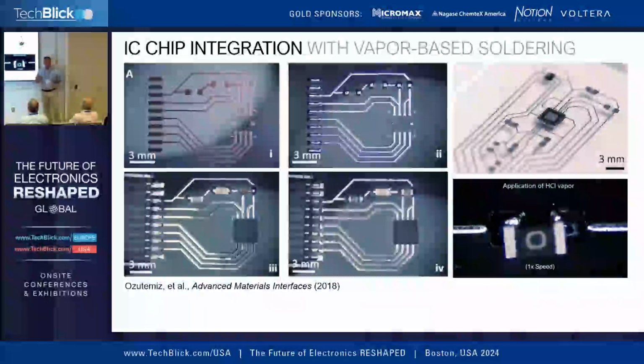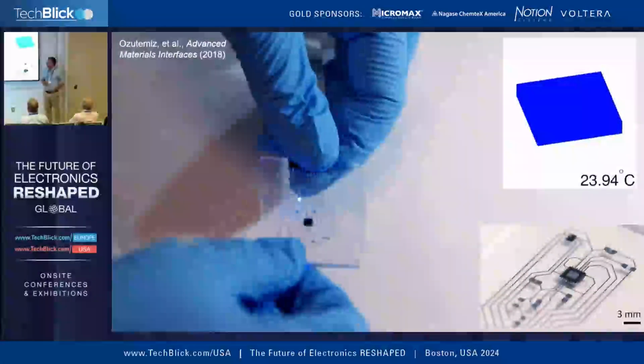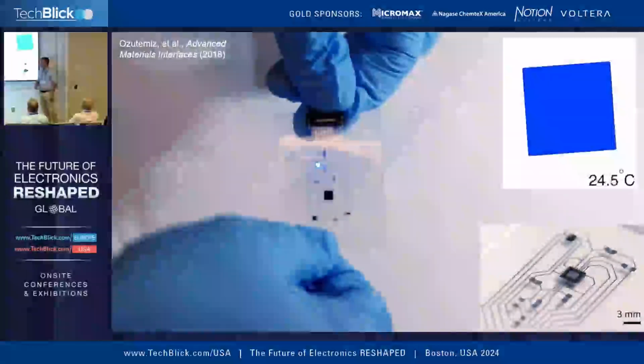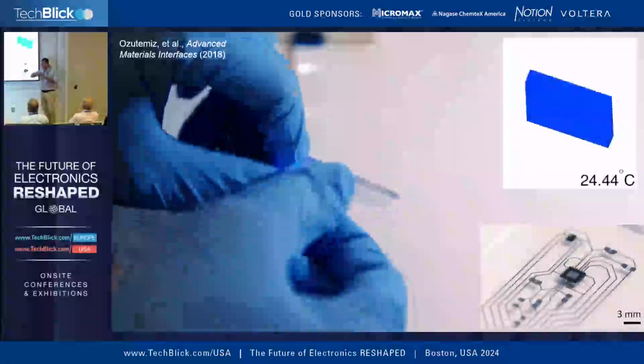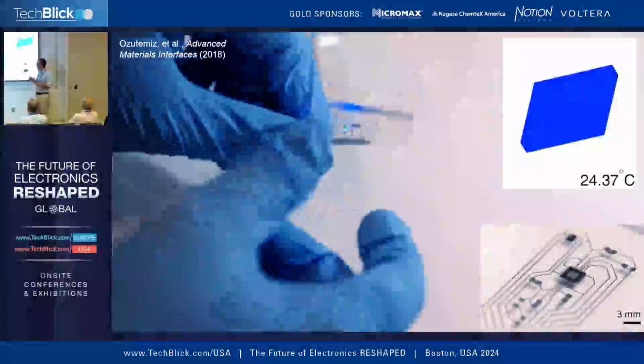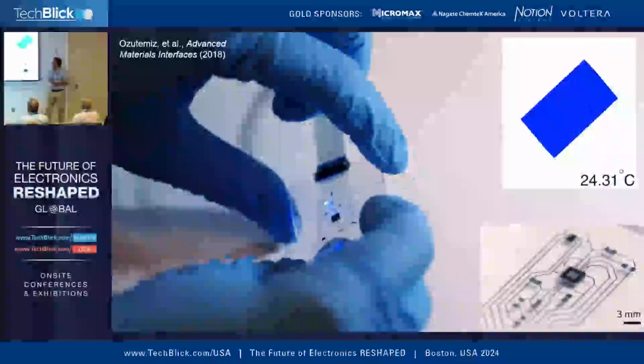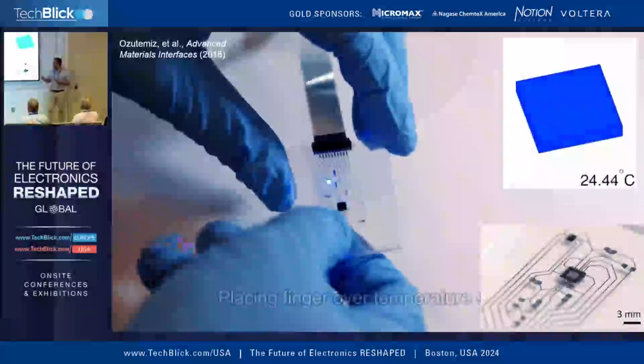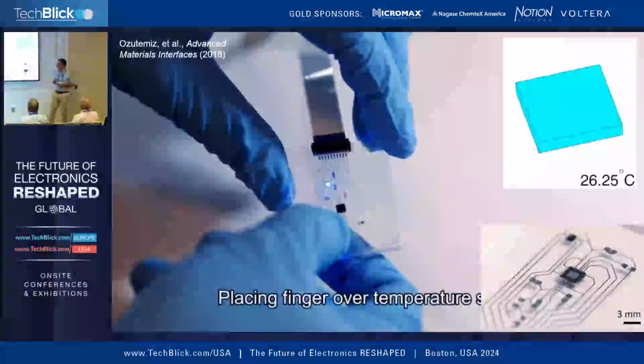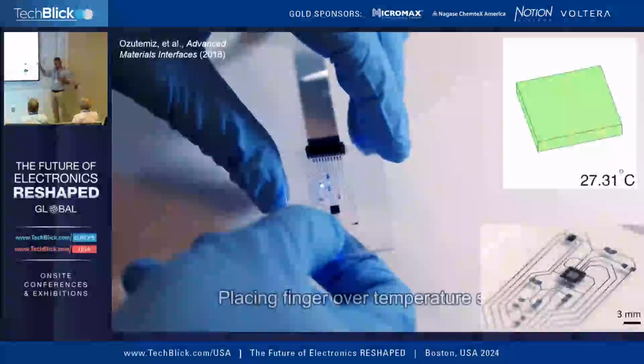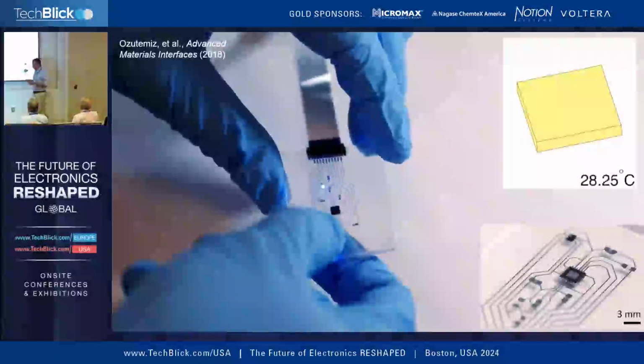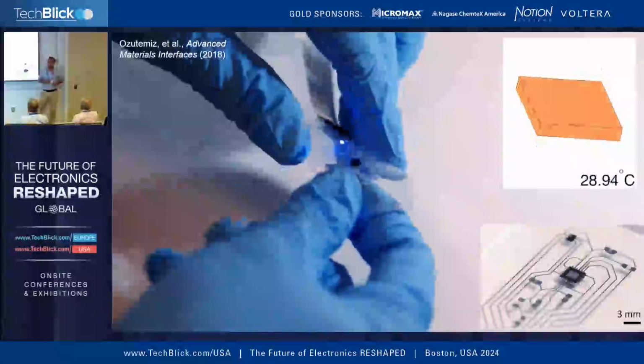And the liquid metal doubles as a solder that we can use to mount these surface-mounted IC chips. So again, quite soft, quite stretchy. The metal interconnects stay quite conductive, even under strain and mechanical deformation. Here we have a digital circuit with the 9-axis IMU and also a temperature sensor. So this is nice in terms of early demonstrations that we were able to show with liquid metal.